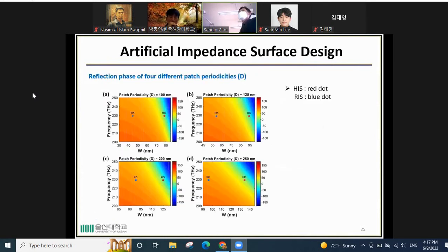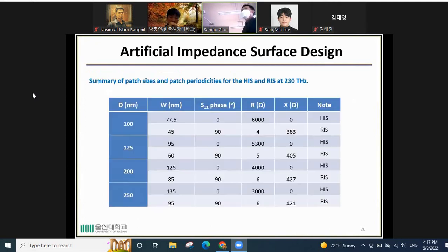And this is the reflection phase of the 4 different patch periodicities. Red dots represent HIS, and RIS is represented by blue dots. And this is the summary of the patch size and patch periodicity for the HIS and RIS. For example, for patch periodicity 100 nanometer, patch width 77.5 is the HIS because of the high surface resistance, and patch width of 45 nanometer is the RIS because of the high surface reactance.